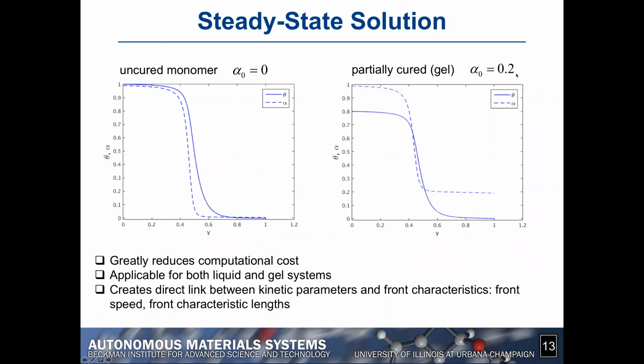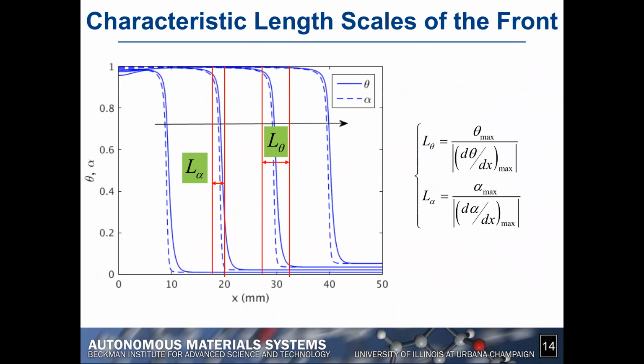The big advantage of the solver that we've developed is that it allows us to greatly reduce the computational cost and to create a direct link between the kinetic parameters and the front characteristics, which are the front speed and the characteristic length. Talking about these characteristic lengths, you have here typical snapshots of the front as it propagates, and there's a length scale associated with the thermal gradient, or the thermal front, and the degree of cure front, L alpha and L theta respectively.